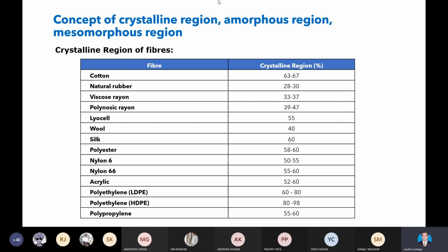Now, as I told you, even if fibers are in the same class, like cellulosic, proteinous or synthetic, you will find that there is a variation. For example, the crystallinity of cotton is 63 to 67%. Viscose rayon is exactly opposite, 33 to 37%. It means viscose rayon is less crystalline as compared to cotton. That's why the strength of viscose rayon is lesser than cotton. But if you see the absorption, dyeing behavior and moisture regain, viscose rayon is higher than cotton because crystallinity is changing.